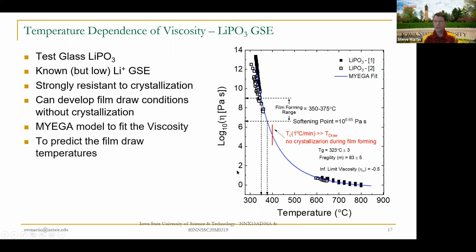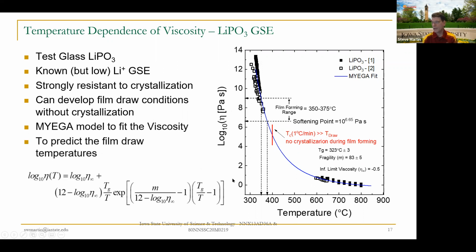So we do experiments to determine this temperature dependence. This is experimental data. And the blue fit is our experimental fit. It's a kind of complicated model to get it accurate enough, but we can do experiments to determine the parameters, and we can predict the viscosity very nicely because the viscosity is not real well known in this region that we need it. So we can predict what temperature to draw our film at.